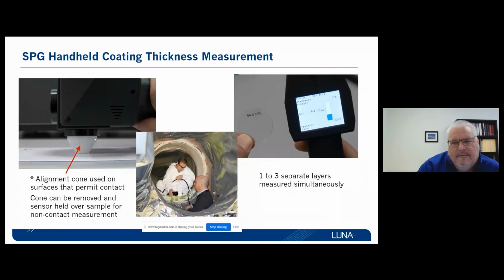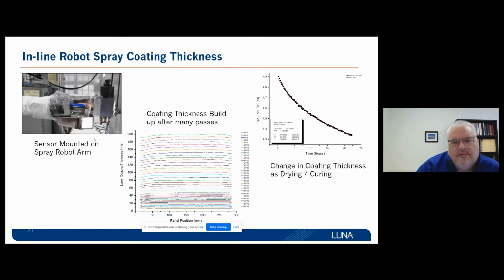So the method is very highly accurate and can be used to measure in these complex geometries, as you see here, measuring these coatings applied to an inlet duct in the center of the picture. And then we, of course, have in-process monitoring, where in the upper left-hand corner you see that Class 1 Div 1 sensor mounted to a spray robot, so that it's actually measuring concurrently with the spray. So we either measure as the coating is being applied or after the coating has been applied, say at the 90% point. The middle graph shows a coating buildup over many passes, and then you can measure the change in thickness as the coating may shrink as it dries, and then predict the total coating thickness at different times.